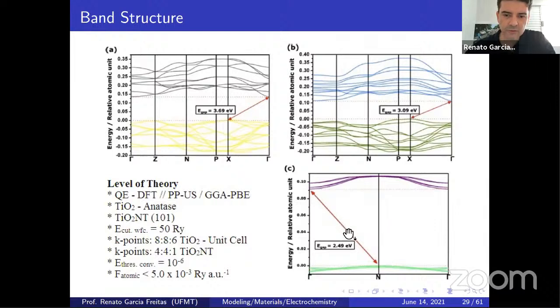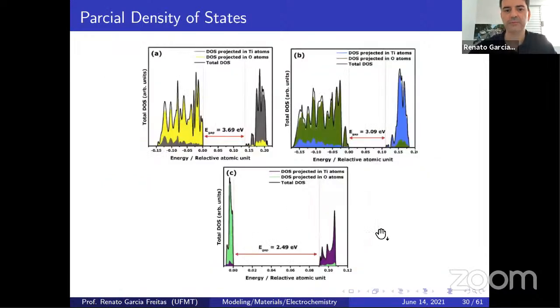And for the titanium nanotube, the Brus equation considers that the gap values are a function of the radius, and the ballistic conduction for sure. So we obtain lower gap values, 2.49, indirect band gap as well for this third system, the titanium nanotube system.